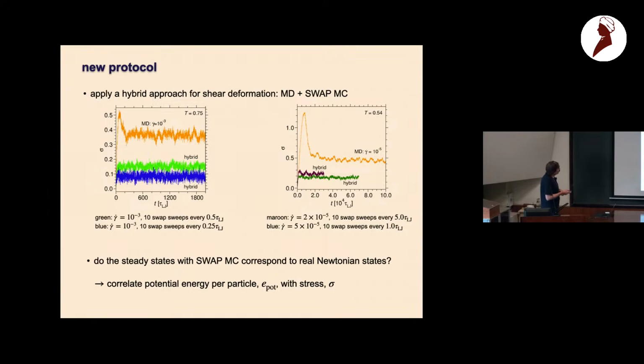This is now at temperature 0.54. And in fact, with the hybrid scheme, we get to stresses, and the response looks very Newtonian-like, which are far below the yield stress, in this case, that we have estimated before from the Herschel-Bulkley fit.